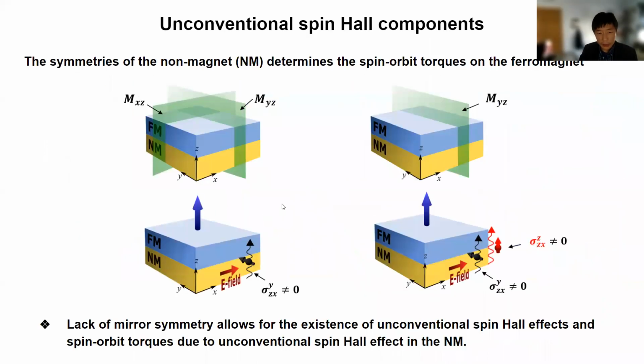To summarize, the idea is to go from these high symmetry materials to low symmetry materials. And the benefit of going to these low symmetry materials is that you can also get a spin current that is collinear with the spin orientation. So this is the component that you want, and this is the component that allows you to switch a perpendicular magnetization.